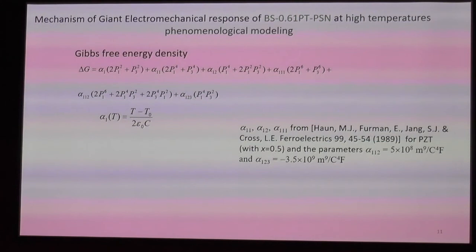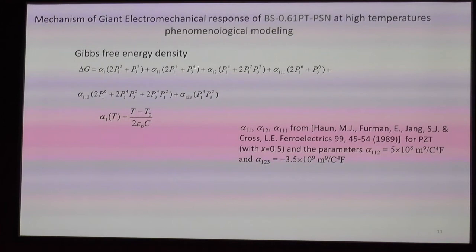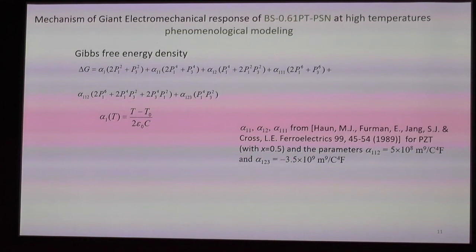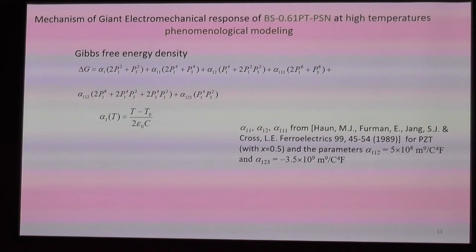We use the standard Landau-Ginzburg-Devonshire theory. Gibbs free energy is expanded as a function of polarization. And from the literature, we can estimate the coefficients. We took the same coefficients as for PZT ceramics, because we don't know them exactly for our material. And to obtain agreement with our experiment, we need to change a little bit these two coefficients.